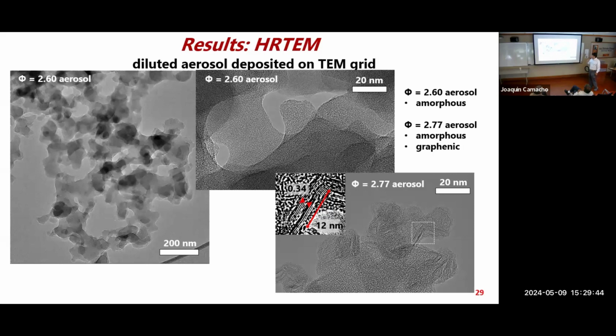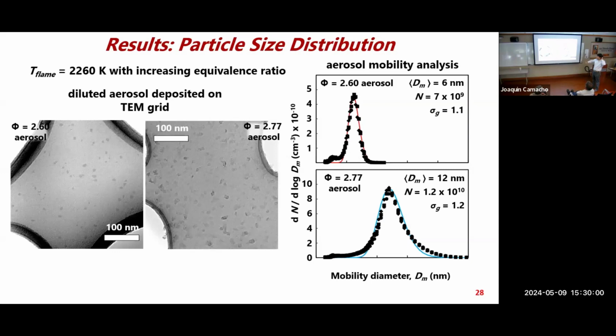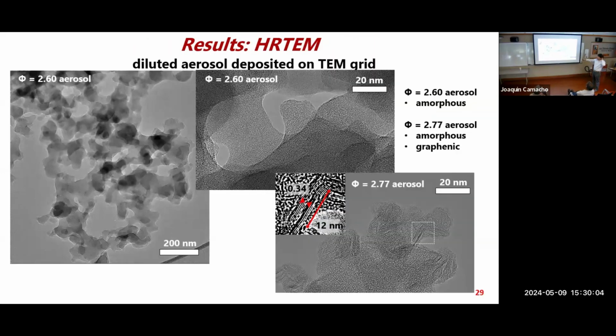And then interestingly, looking at higher resolution images, it's not the same uniform structure of carbon materials. We actually see a lot of amorphous structure of particles. So here's one example. If you go across this whole sample substrate, you have these big blobs of pretty much amorphous materials. There's no crystal structure there really, but in some areas there are crystal structures. You see these strands of graphene ribbons basically. So if you look at this, measure the distance between these fringes, that fringe is the graphene layer, graphite layer distance. So this is one evidence of the graphene structure.